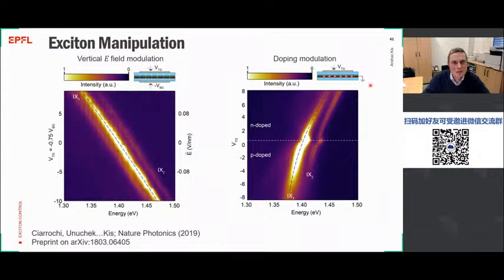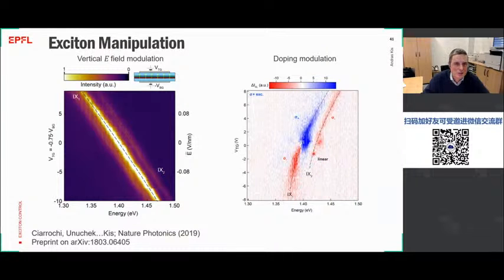But if we also allow the charge carriers to go in and out of the heterostructure, then at the same time we can also dope. And this doping is interesting because now, in addition to just changing the energy, we can also change the polarization of the light that's coming out of the device. So for strong electron doping, we can have these two transitions which correspond to the same excitation and the opposite polarization. But then for hole doping, we actually switch to a regime where the emission becomes oppositely polarized to the excitation, and the other peak becomes linearly polarized, so we can no longer resolve it by using circular polarization.